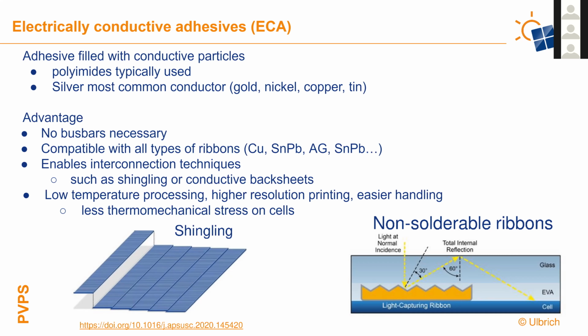This is one study on electrically conductive adhesives. One thing found is that the chemical composition, cure conditions, and handling of these materials actually impacts their fracture behavior. So there's some variety in what's being reported in the literature on reliability of these, and it seems to come down to material handling or manufacturing of the materials.